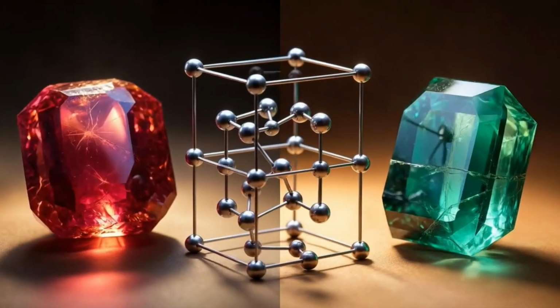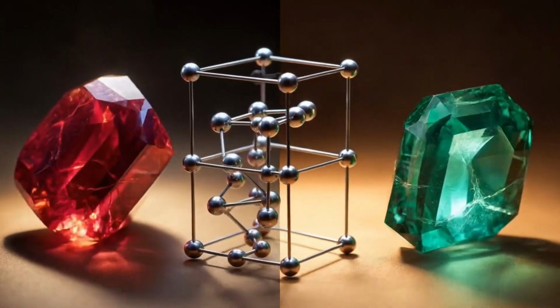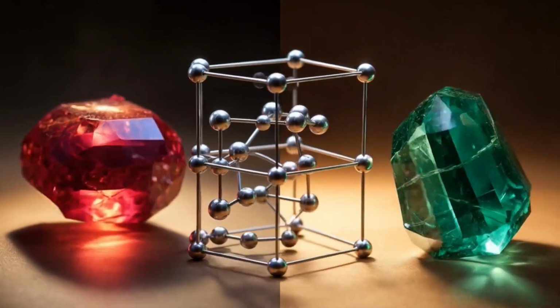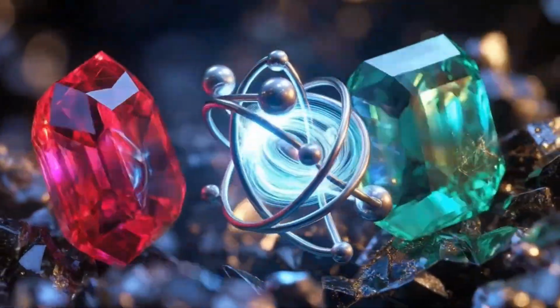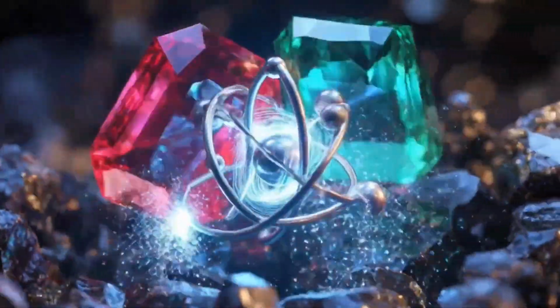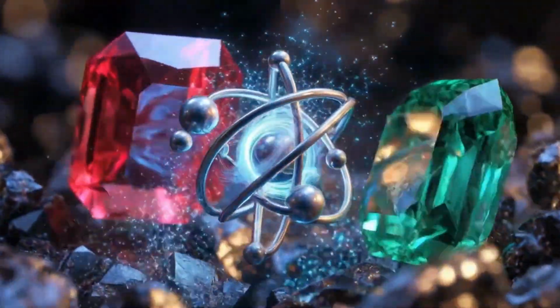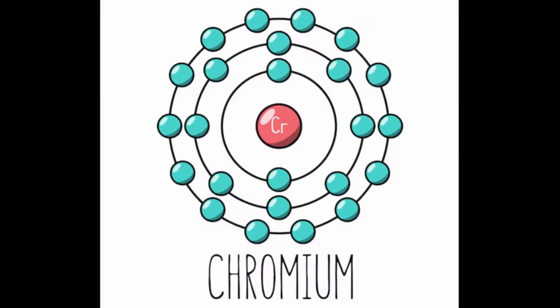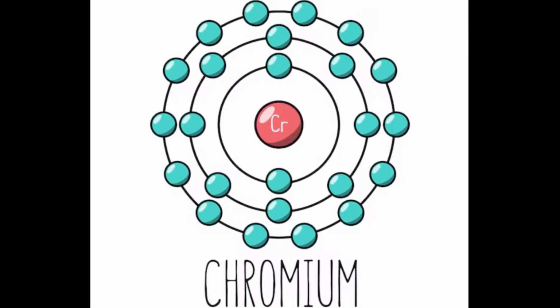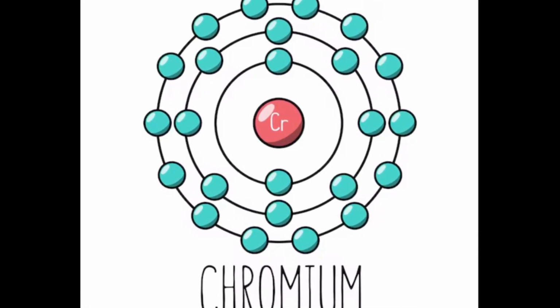mineral. The distance from the chromium ion to the surrounding oxygen ions is slightly less than 2 angstroms. This distance creates an electric field of a certain strength. The field splits the energy levels of the electrons so that the energy difference corresponds to green light. Green is absorbed. Red is reflected.